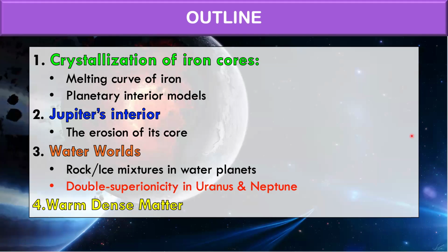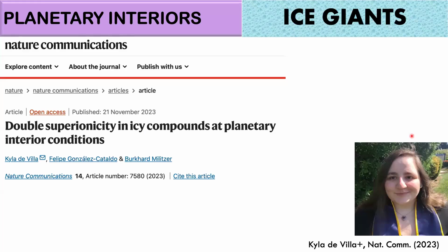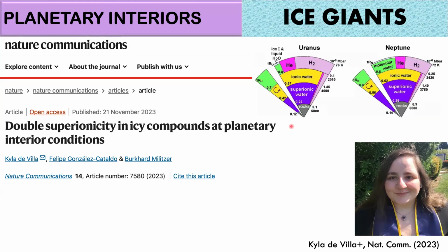Okay, and I want to tell you a little bit about a project that Kyla, a student in our group, presented a year ago here in a CIPS seminar, which is a very cool project where she discovered this new phase that we coined double superionicity. Basically, Kyla focused on Uranus and Neptune and the composition of these planets. It has been suggested that they have a lot of this superionic water, but they also have hydrocarbons mixed up with nitrogen. So at the extreme pressures of these planetary interiors, you form new materials in the solid phase. Even if the temperatures are high, new compounds are formed.